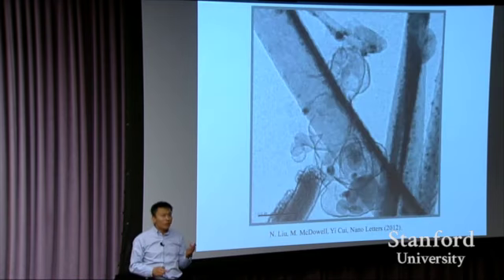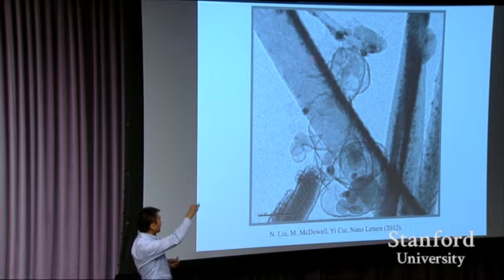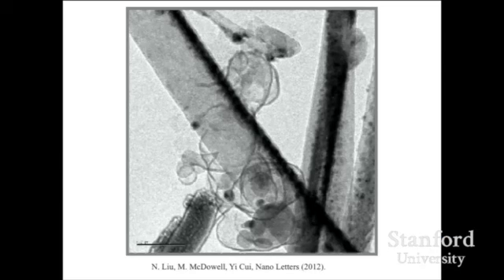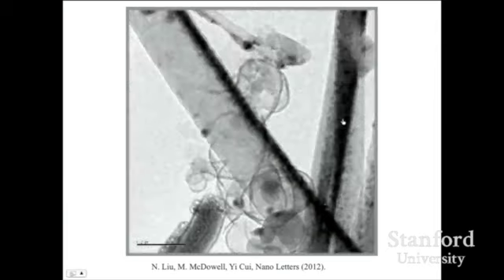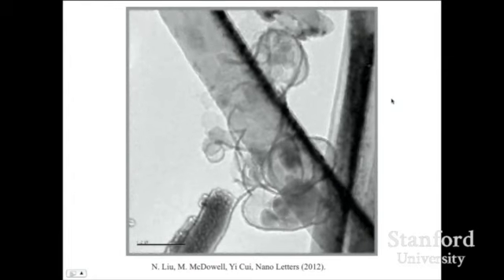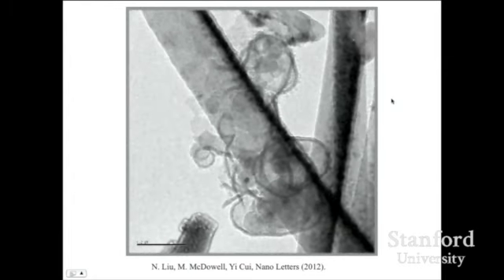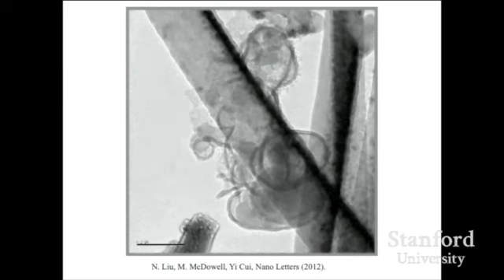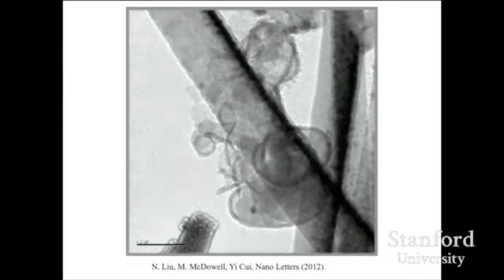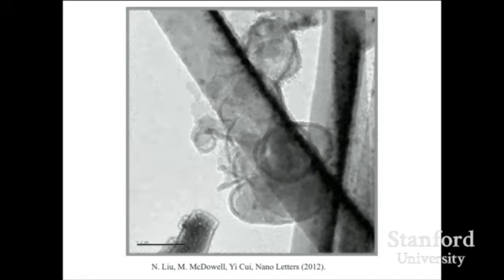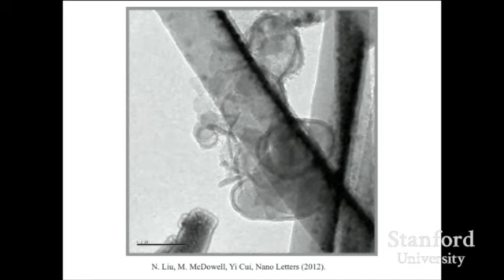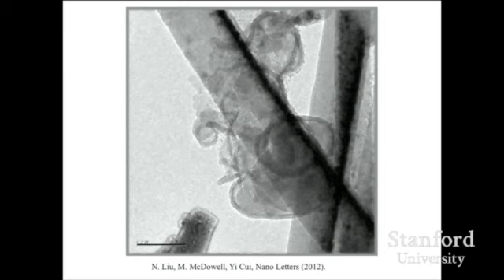Now let me show you a video to convince you this idea is really working. This is a yolk-shell structure with silicon with a carbon shell. You start to charge up these batteries. And then you can see the silicon expansion is happening, filling the empty space. You leave it just exactly right. If you talk to our EE professors right here, you say, I want 10 nanometer silicon oxide, I want 100, they can give you exactly that thickness. Using that type of synthesis, using silicon oxide as a sacrificial layer, you can engineer this empty space, allowing the volume expansion to just exactly fit.